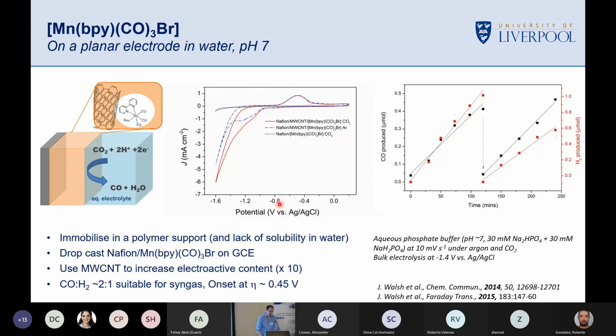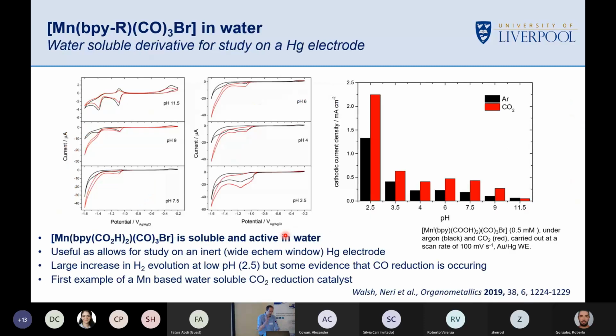And we produce CO, not in fantastic Faradaic efficiencies, it's about 2 to 1 CO to hydrogen. But we do this at reasonable onset potentials at neutral pH, and we're quite happy with those sorts of current densities on a planar electrode. So we did that for a number of years and thought that's rather nice, and we put that to one side. And then we sat back and thought about, well, can we take this behaviour in the presence of organic acids, where we can vary the strength of the organic acid on the catalysis, into water?